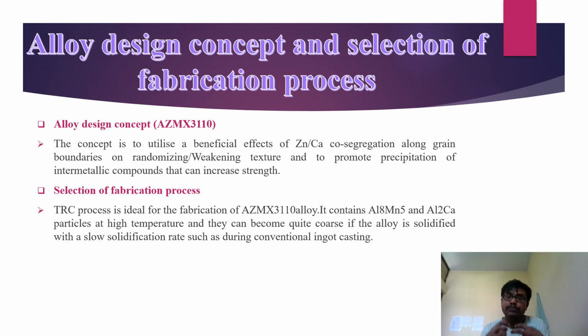So the author did some thermodynamic calculations with manganese, and found what will happen when manganese is added to the magnesium, zinc, calcium, aluminum alloys. It will form an intermetallic compound with aluminum, and that is Al8Mn5. When Al8Mn5 is formed, the possibility of forming Al2Ca is decreased, because the Gibbs free energy is more negative in the case of aluminum and manganese.